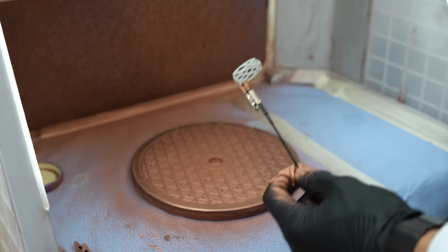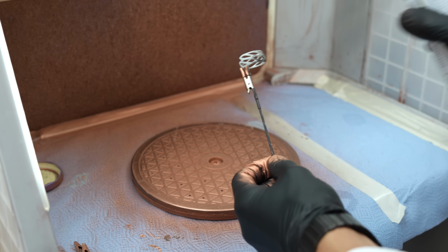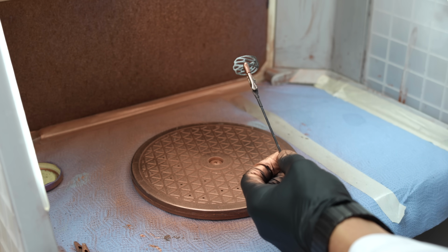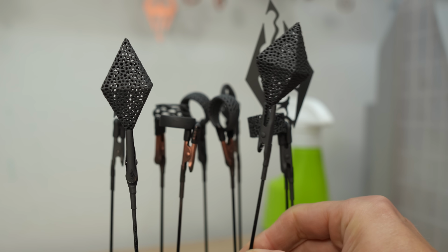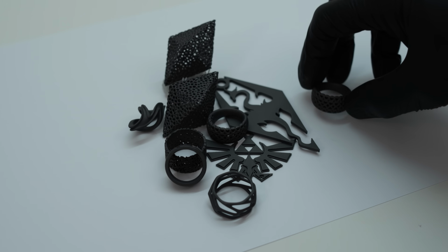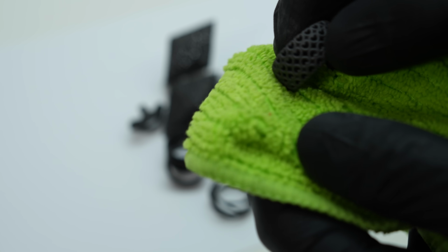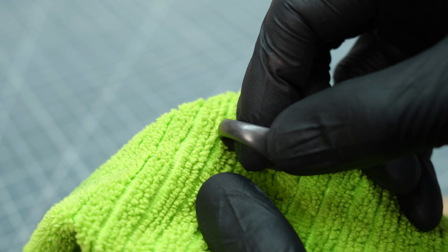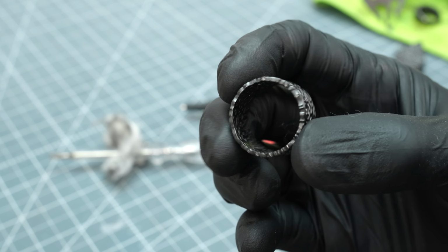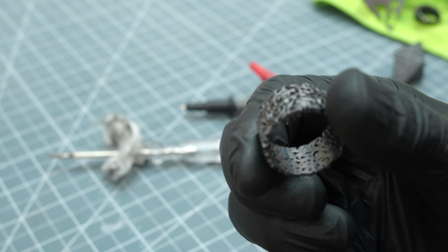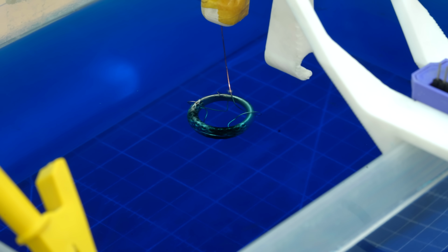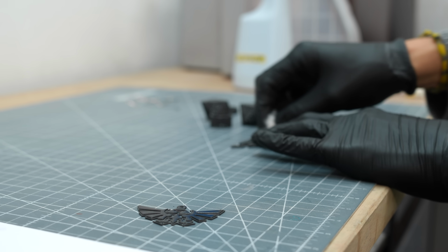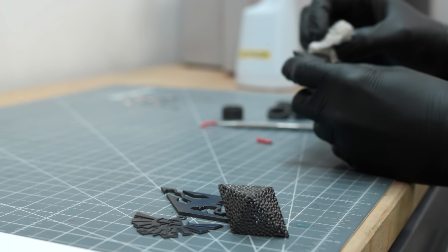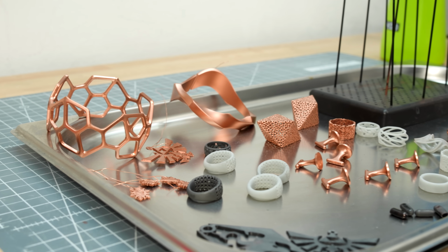Before I explain how I make my own graphite paint, let's first test the graphite spray. Just spray it on and let it dry. A common mistake when using these graphite sprays and paints is forgetting to polish them. Sure, they look beautifully black, but the conductivity is too low. Polishing can significantly improve this. I use a microfiber cloth for the job. A quick test? Yes, it works very well. Now, onto the remaining pieces. In the end, I coated all the jewelry prints, once with copper conductive paint and once with graphite. I wanted to see if I could notice any difference at the end.